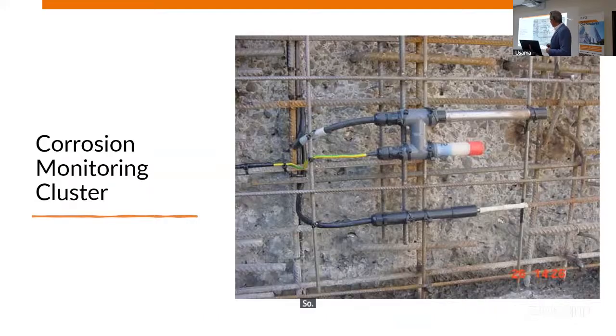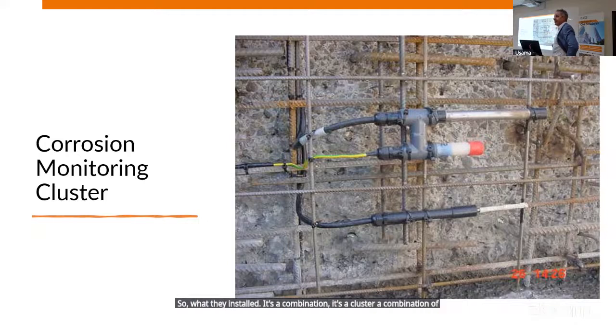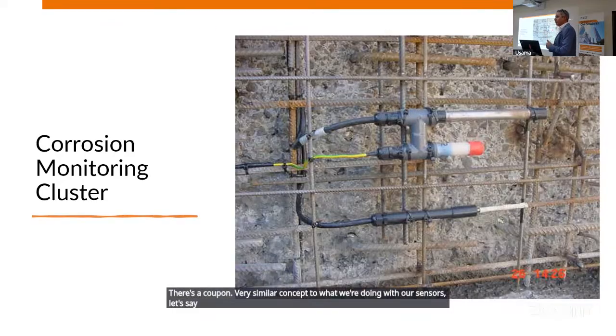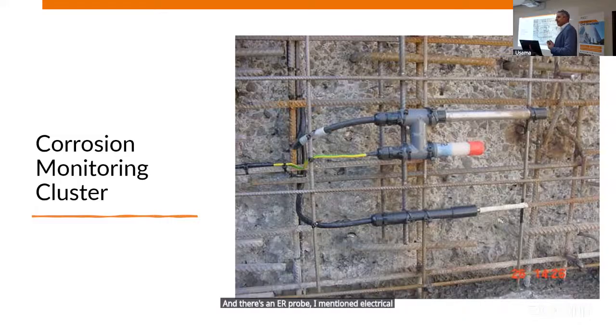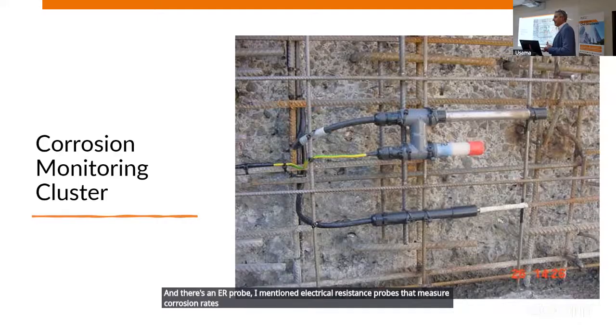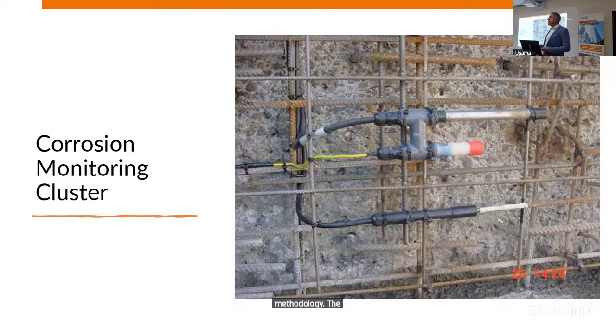So what they installed is a cluster combination of three types of monitoring devices. There's the reference electrode, a silver chloride reference electrode. There's a coupon, very similar concept to what we're doing with our sensors, let's say an early generation of what we're doing with our sensors. And there's an ER probe. I mentioned electrical resistance probes that measure corrosion rates. So they really have a robust corrosion monitoring methodology. The limitation is that the data was collected manually, and after time, they stopped collecting the data.